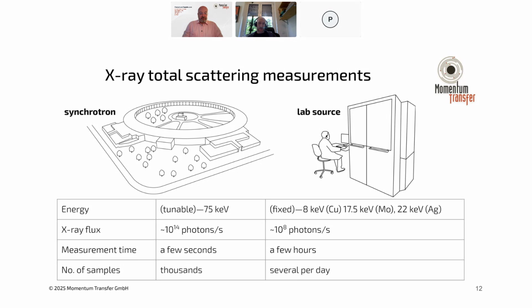So at the beam line that we work at, where these X-rays are directed, we collect something like 10^14 photons per second. So with this kind of flux, you can do measurements in a few seconds of the very high quality that you would need hours to collect with a laboratory device. And we can collect thousands of measurements in a day. So that allows us to bulk up the statistics on what you can do in terms of observations.